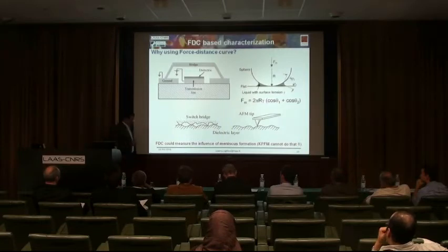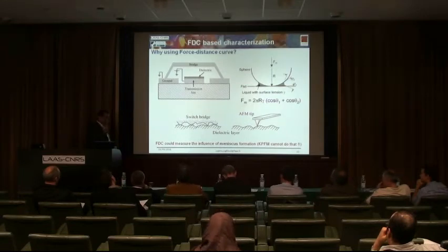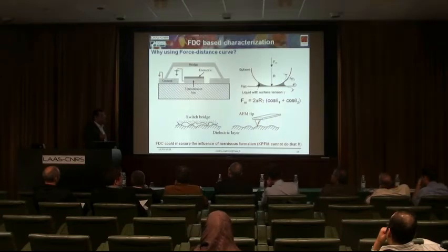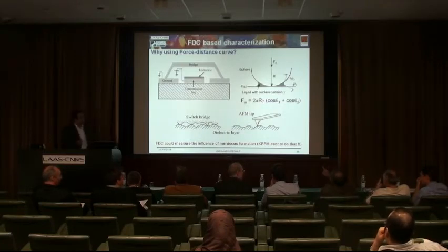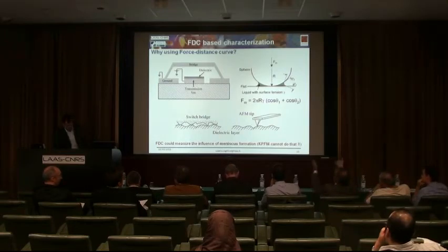Well, let me think. It depends first on the contact shape we have. In this case, we have a spherical contact. While it might not really simulate the real asperity in MEMS switches, it might be different. I think it also depends on the surface tension of the liquid layer. Actually, it depends on the contact angle, on the hydrophobicity of the surface. If both surfaces are hydrophilic, meaning the contact angle is less than 90 degrees, it turns out they'll be concave shaped.